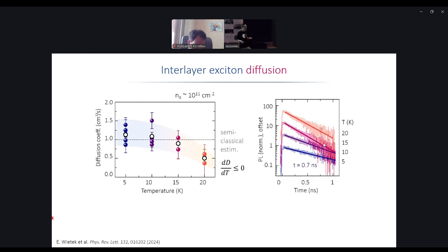And we have a lifetime that is short, right? We have a heterostructure with a nanosecond lifetime. And this is important to consider. And I will not tell you anything too radical by saying that, well, the coffee machine disagrees, that if you think of what you said, right, radiative recombination, this is an argument you will hear a lot, and the argument is not incorrect, that if you go from a monolayer exciton to this type of exciton, the radiative recombination is suppressed, right, because the wave function overlap is smaller. We would all agree. However, if you have a system, and most realistic systems do have non-radiative channels, these channels do not magically disappear just because we build a heterostructure and increase the radiative lifetime.